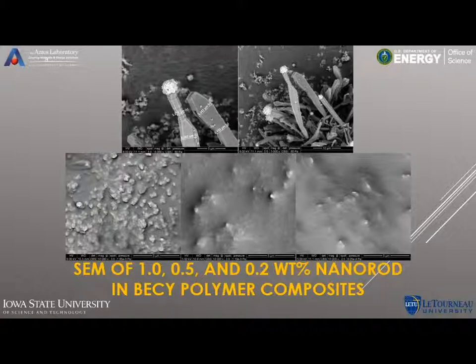We've got a lot of rough material in there, that's the nanorods, for the 1.0, and much less for the 0.2. And you can also tell from this that they're pretty evenly dispersed. In the 1.0, it's pretty much rough all over the surface. It's not clumping together in certain areas. And so that's good because we want the filler material to be evenly dispersed in the polymer.